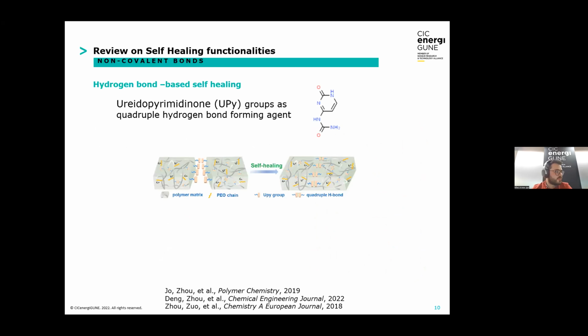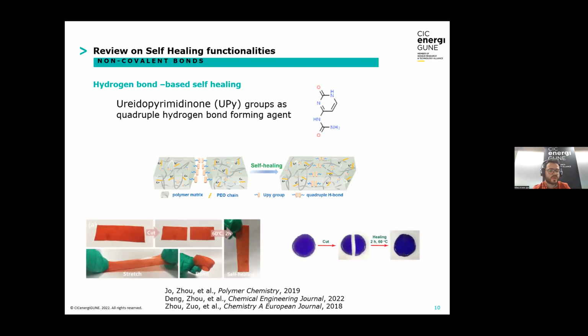If the polymer electrolyte, as we can see in this figure, suffers a cut due to the formation of a dendrite, for example, or a mechanical strain, the hydrogen bonds would allow repair of this rupture. Several examples in the literature show how the membranes self-repair after performing a cut, generally through the application of heat. This is just a lab example, as we saw in the previous presentation.